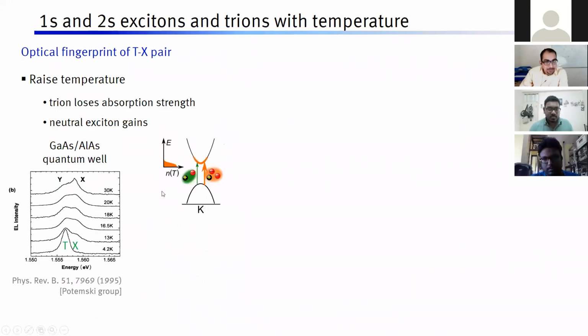Yeah. So let's take the case of a doped semiconductor. There are some excess electrons available, which will be in the conduction band at a certain temperature, right? And then there is a valence band. Now, if you want to create trions, then you need these excess electrons, because a trion is a 3-particle state. So then you can create some trions. But if you have these electrons which are frozen at the center of the band, then excitons are very tough to create, because for creating excitons, you need an empty state here. Then only you will be able to excite an electron from here to here and create a hole. However, now that is frozen. So you create fewer excitons and more trions at low temperature, right?